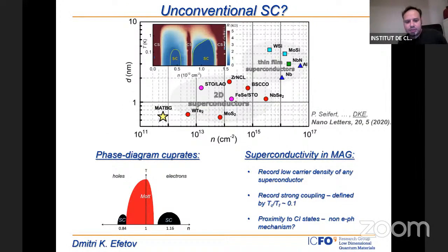I really want to take a second to contrast this type of superconductivity. First of all, we now have a correlated electron system with superconductivity originating from it. The immediate comparison, also looking at the phase diagrams, is with other unconventional superconductors, like the cuprates, but also the heavy fermion systems or the pnictides. Naively speaking, the similarities are big. As in the case of cuprates, we get Mott insulators without doping, but when we dope the Mott insulators, we get superconductors left and right. This is reminiscent of the phase diagrams we see here.